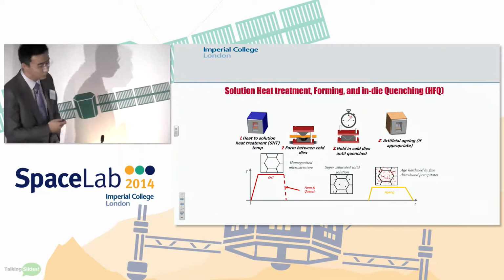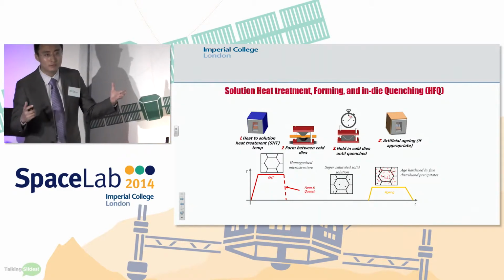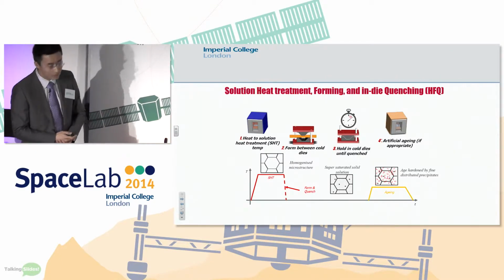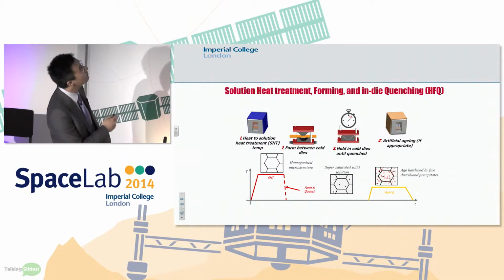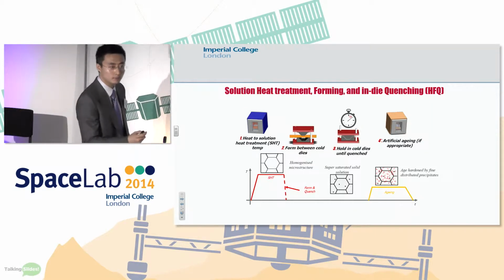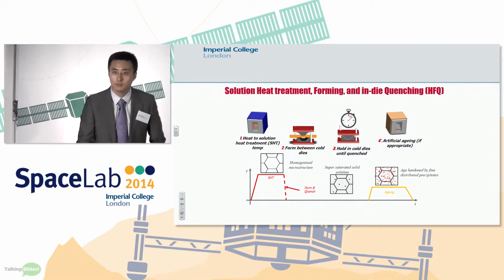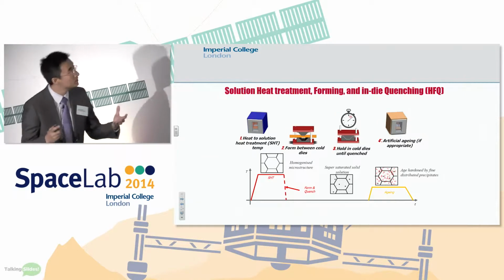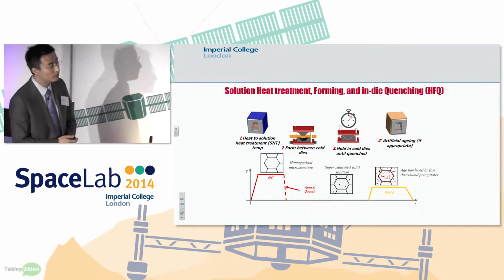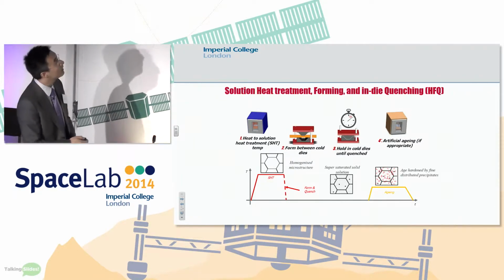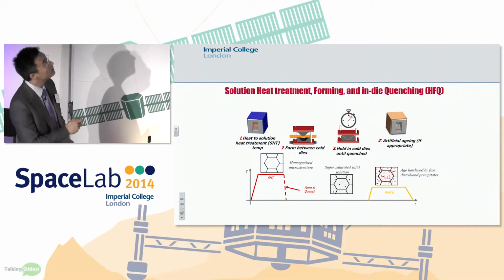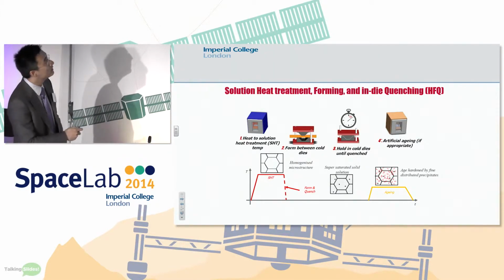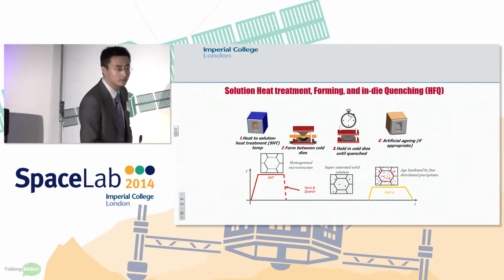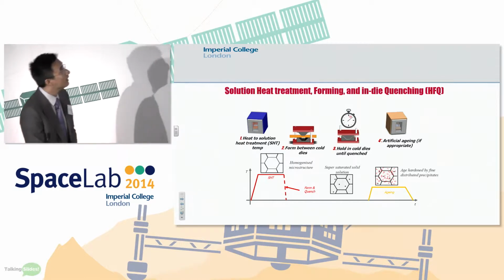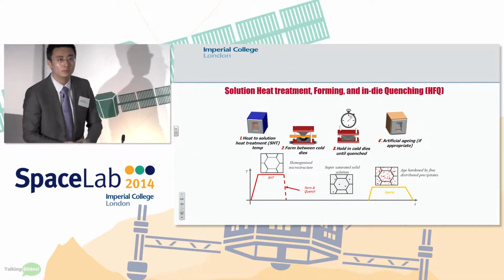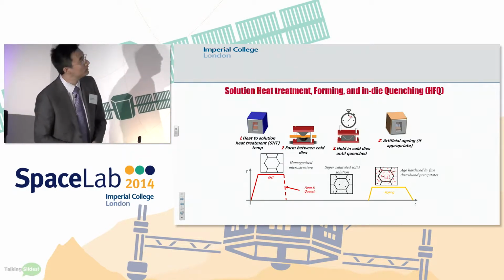This is a very novel forming technology that combines metal forming and heat treatment in one operation. Since we form the components at solution heat treatment temperature, the ductility of the material is very high, so we can form components with very complicated geometry. And since we are quenching in the cold die, a supersaturated solid solution state is obtained after forming. After artificial aging, we can retain the full mechanical strength of this material.